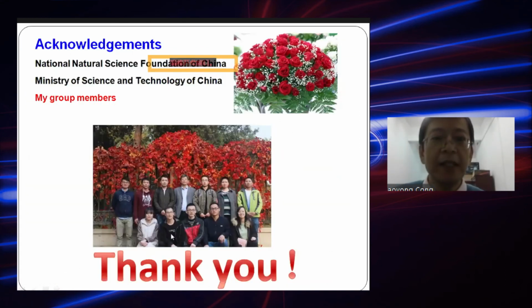This is a summary of this part. We obtained a large elastocaloric effect with an adiabatic temperature change as high as 31.5 Kelvin in nickel-manganese-titanium alloy, which simultaneously has a large unit cell volume change across the phase transition and good mechanical properties.